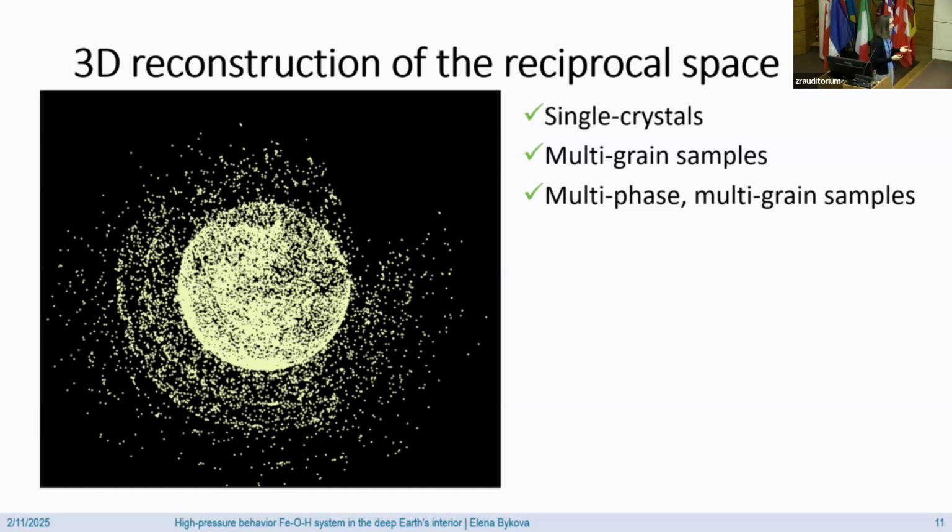But the nice thing about single crystal XRD is that in the software you can just manually rotate this reciprocal space, search for rows of reflections, and then select some whose pattern you see. You need like 20 peaks, not hundreds. And then the software can calculate the unit cell parameters, the orientation of the crystal, and then find the rest of the reflections.